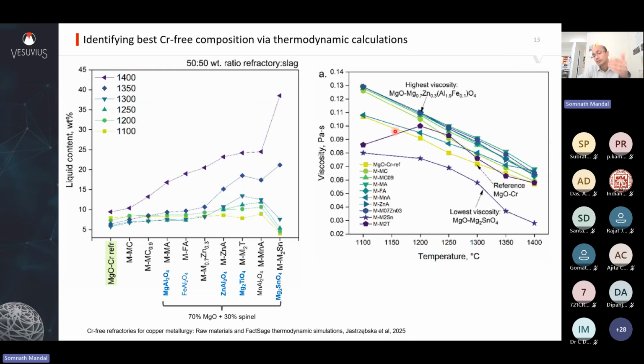If you want to do real viscosity, what you need to do is grind a 50-50 mixture of this slag and refractory, and then you put it in a high temperature platinum viscometer where you have a spindle and you have a crucible, and then you heat it and you rotate your spindle, and from the torque measurement, just like a room temperature viscometer, you measure the viscosity at high temperature of slags.